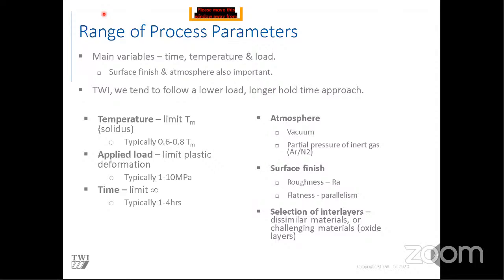The other important consideration is which interlayers you use. Most materials you can diffusion bond with no interlayers - you don't need any - but there are certain combinations, particularly dissimilar materials, where an interlayer is required. That's typically to disrupt or react with the oxide layers present in the parent material.